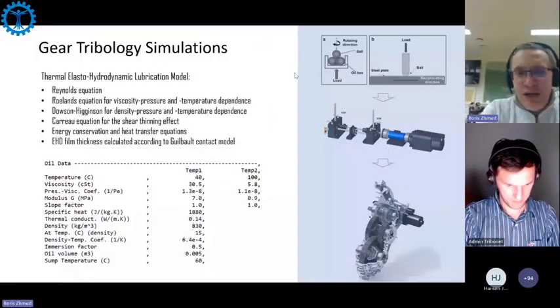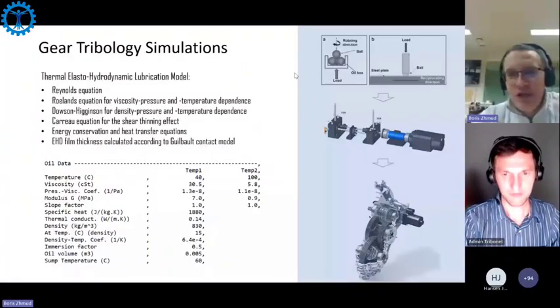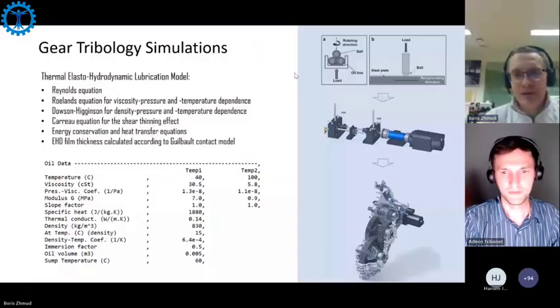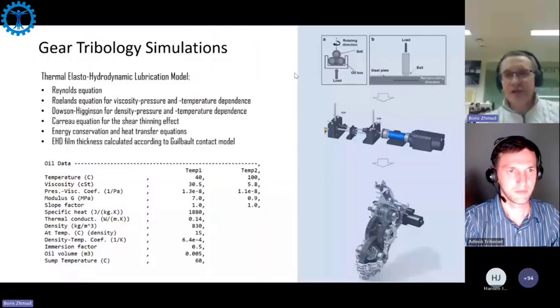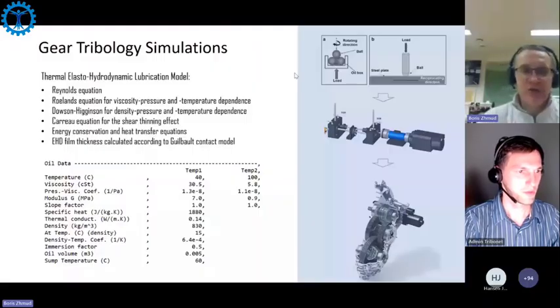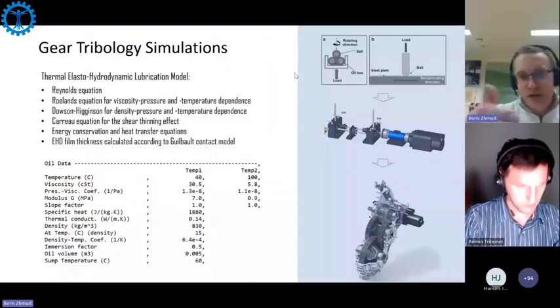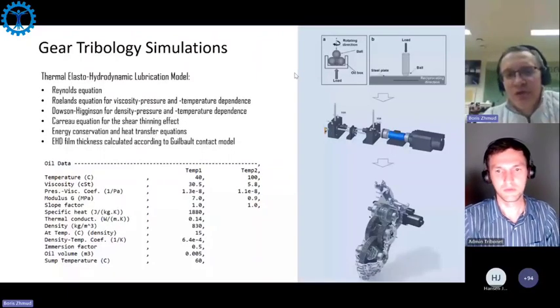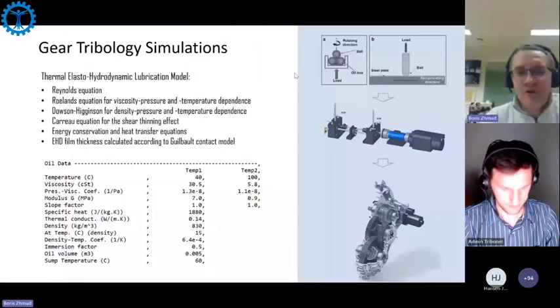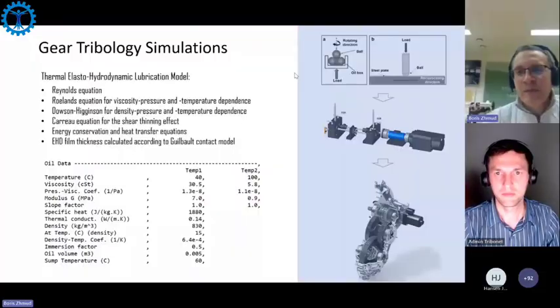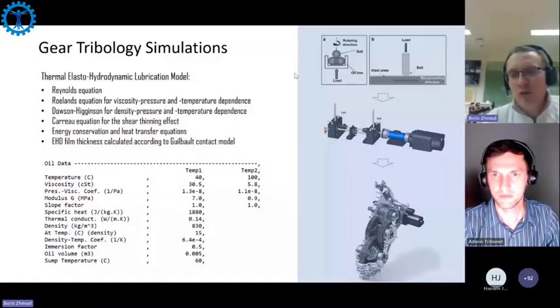And really what we try to do, we try to build the whole simulation chain when you actually bring together experimental results. Experimental results are used to calibrate digital twin, and digital twin simulations are used to actually simulate your actual appliance. So we go from basic tests, which are used for calibration of your model. From this calibration, you basically have a lot of parameters which you need to enter, parameters for lubricants, how you find them. To find those parameters, they are not part of specifications. You need to basically get experimental research to find those data. We use those data as fitting parameters for the model. Then we can validate model by using FZG testing, and after model is successfully validated, we go to full appliance simulation. We can simulate basically the whole gearbox.